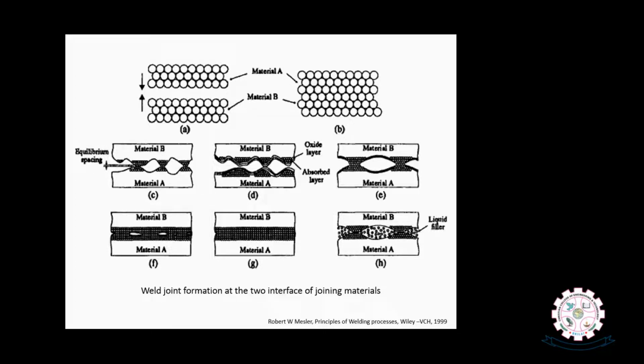The main objective of applying heat or pressure is to bring the maximum number of atoms belonging to both the surfaces which are intended to be joined to a distance equal to the interatomic equilibrium distance. If we have more such atomic pairs at the interface whose distance is equal to the equilibrium interatomic distance, then we have a strong joint. So the strength and the quality of the weld joint depends on the number of atomic pairs having a distance equal to this equilibrium spacing between them. So the objective of applying heat or pressure in welding is to bring as many atomic pairs as possible to this equilibrium distance.